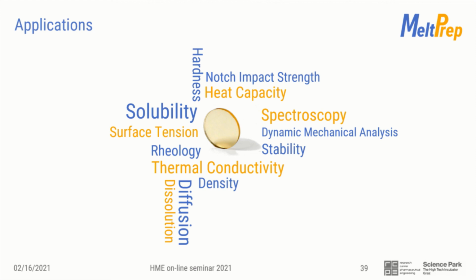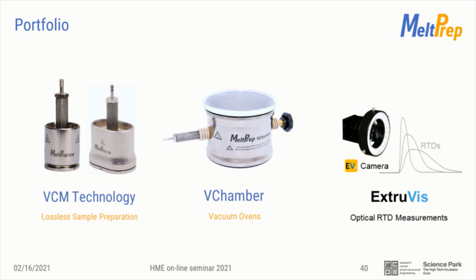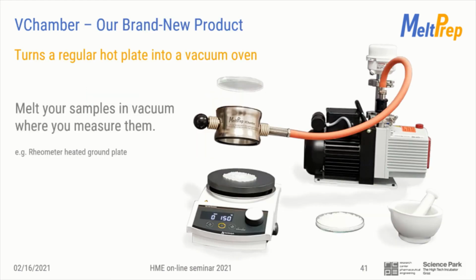Finally, I'll give you a short overview of the entire MeltPrep portfolio. You already know the VCM technology for the lossless sample preparation, but there is more than that. The second innovation is called the V-chamber. The V-chamber turns a regular hot plate into a vacuum oven. Place your sample on the hot plate, then put the V-chamber over it, and you can apply vacuum and melt or dry your sample directly under vacuum on your hot plate. You can also think of melting it where you measure it, for example, on the rheometer ground plate.